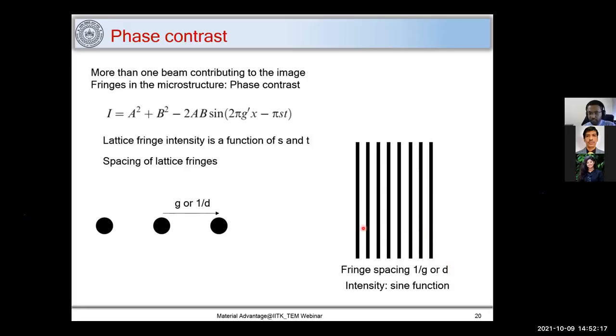And how does the fringe intensity vary? It varies with a sine function, because here there is a sine function. So intensity varies with a sine function in these fringes. Now let's consider 2 more spots here in this way. You can see that these spots were widely spread and these are narrowly spaced. So when I talk about these spots, where will I get fringes? These spots are in this direction, so fringes will be perpendicular to this direction. So this will be horizontal lines. These will be the fringes which you obtain from these 2 spots. And you can see these spots are narrowly spaced, so these fringes will be widely spaced.